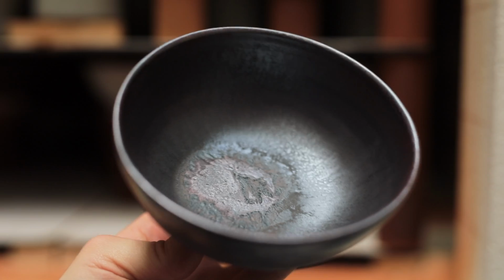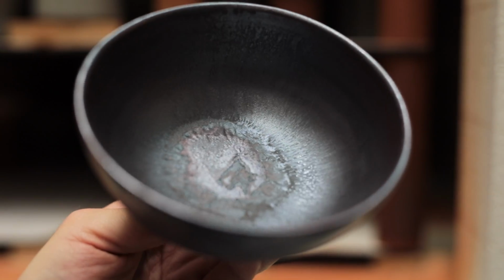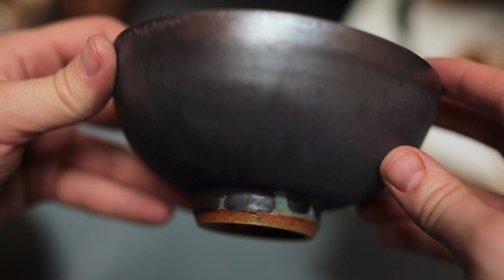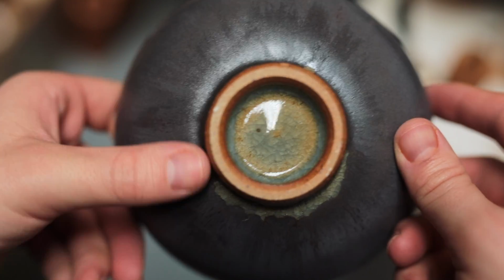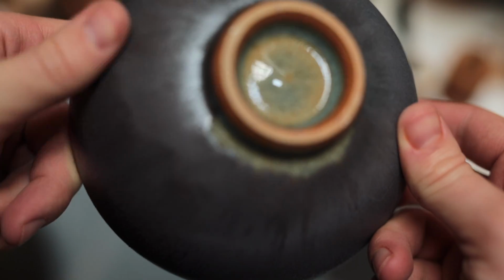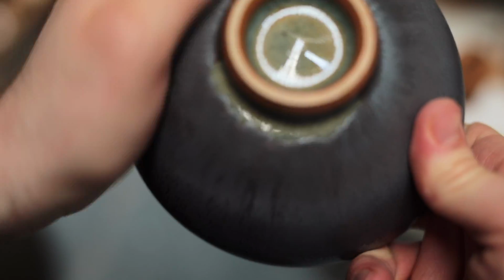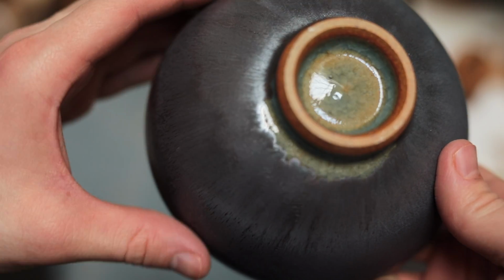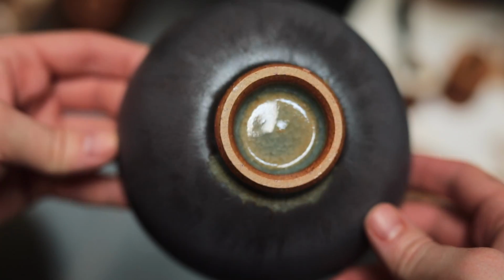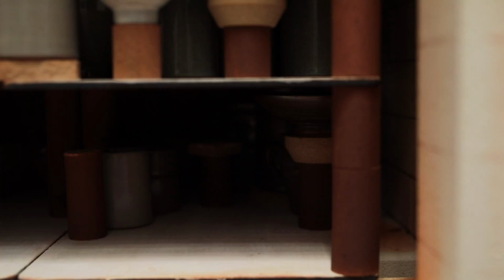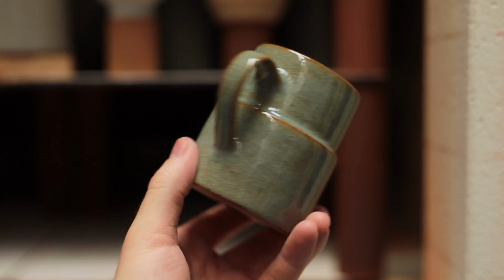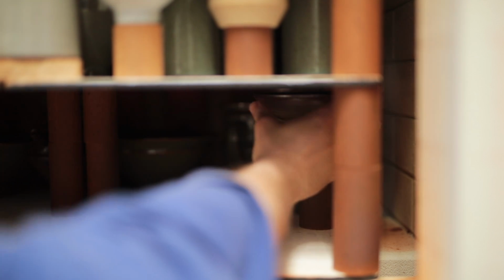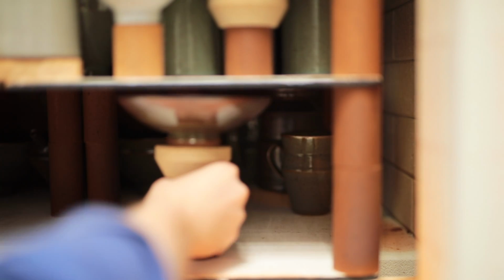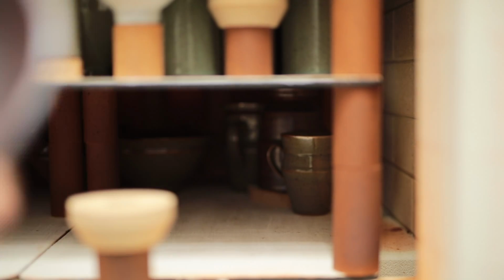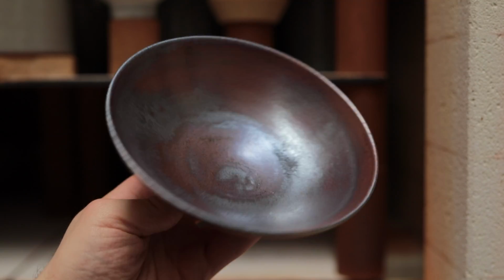Next, here's a bowl coated with black iron oxide and refired, like you saw me brush over the pot with bronze inclusions earlier. For some reason, I was under the assumption that black iron oxide would react and fire in the exact same way as the yellow ochre iron oxide I've been using, and despite them being very similar, the black iron oxide has left a much more consistent surface. And if this means I have to do less refirings overall, then that's a good thing. So I'll definitely be testing this more. Here's another iron-coated bowl, fired atop a rather precarious prop system, which helps me to squeeze more into this bottom layer.